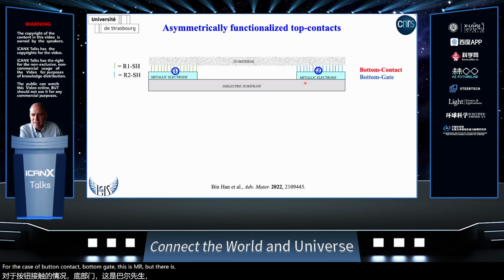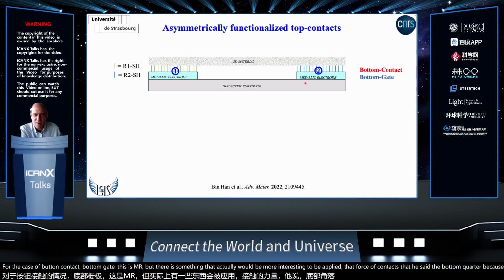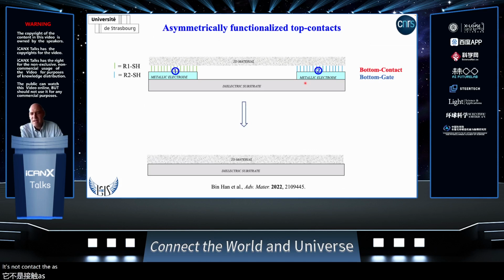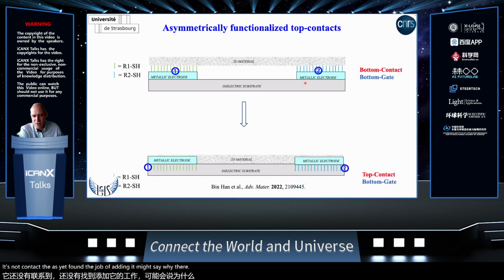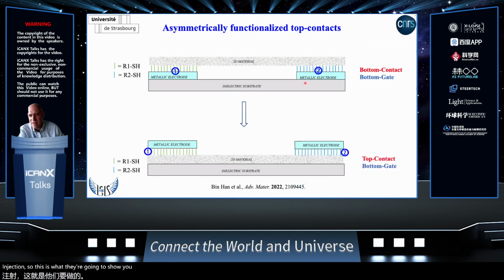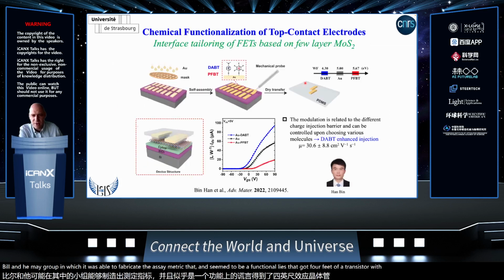Now, this is something that has been demonstrated for the case of bottom contact, bottom gate transistor, but is something that actually would be more interesting to be applied for top contacts instead of bottom contact, because of course the top contact has the advantage of having a much wider area of injection. So this is what I'm going to show you now, a recent work that just appeared in the literature, done by Bin Han in my group, in which he was able to fabricate asymmetrically functionalized top contacts for field effect transistors based on MoS2.